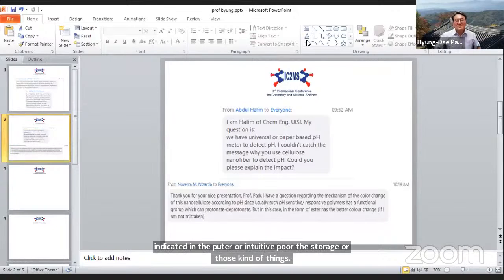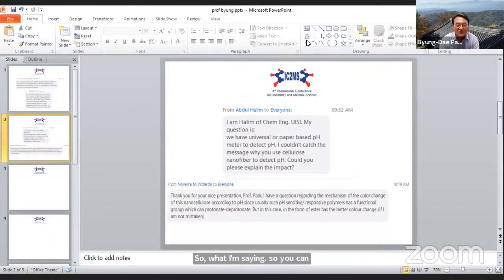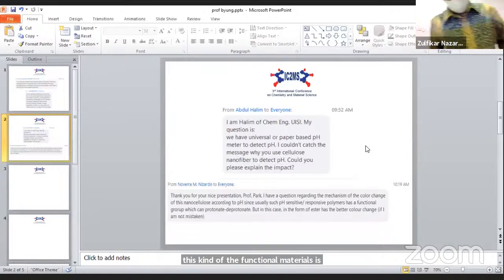So what I'm saying is that if you have any solution using pH indicator without the nanocellulose, without the releasing, without the leaching, then you have something better than mine. You can find that. That's a good thing. But it seems to me when you have a pH indicator by itself, it may be soluble in water and then it is released. That's going to be a problem in the future. That's why I use the nanocellulose as a carrier for this kind of functional materials. Is that enough? Yeah.